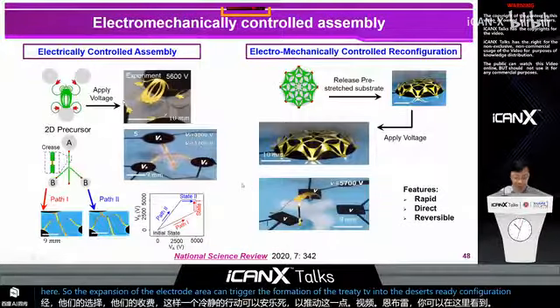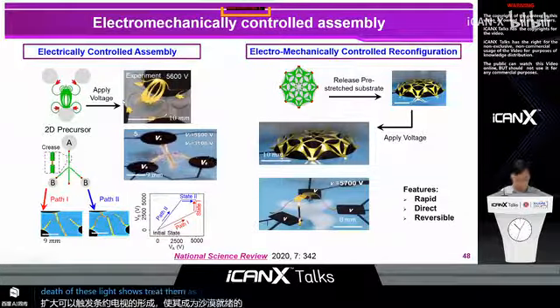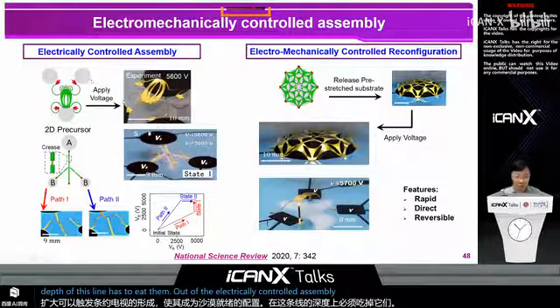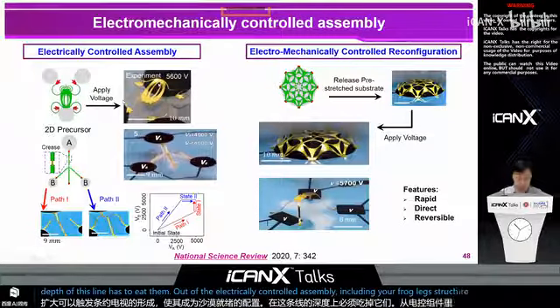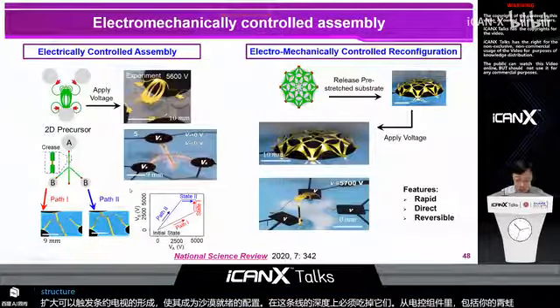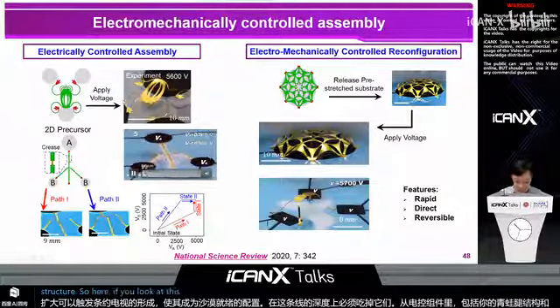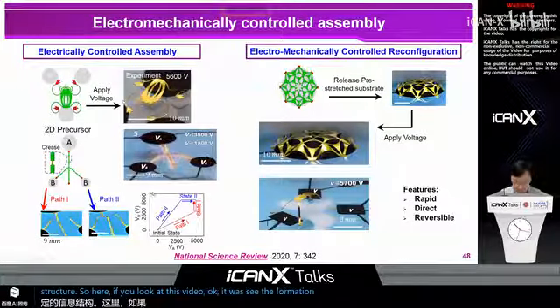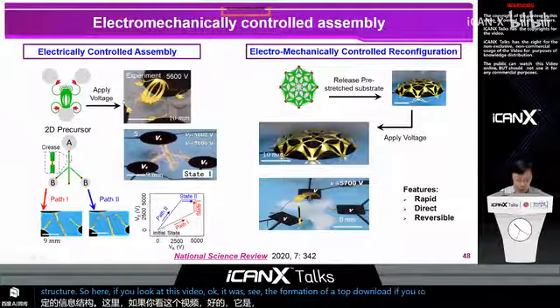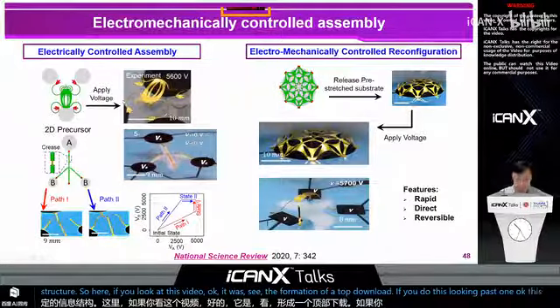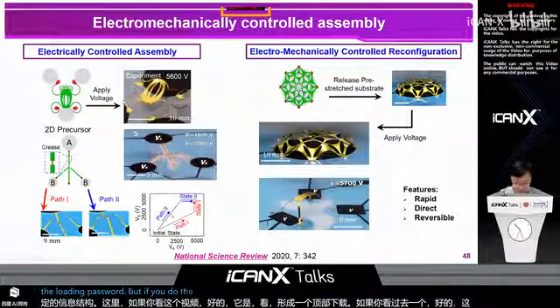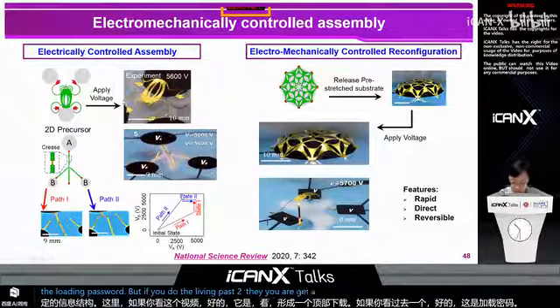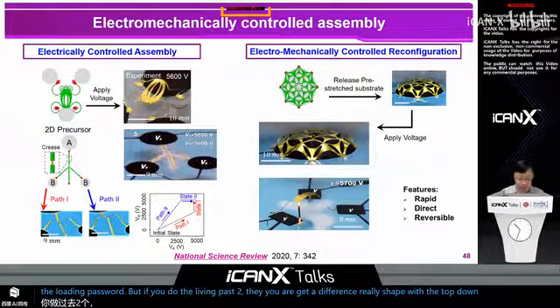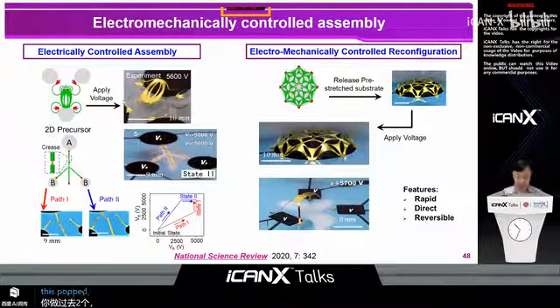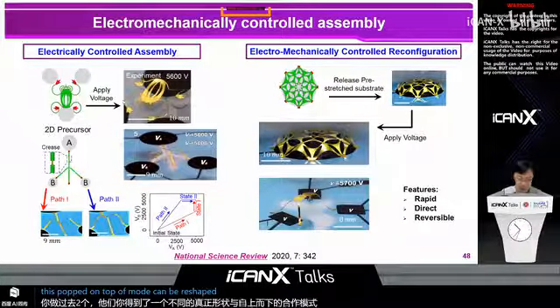On the left of this slide shows two examples of the electrically controlled assembly, including a frog-like structure and a bistable mesostructure. So here, if you look at this video, you will see the formation of a pop-down mode if you do this loading path 1. This is the loading path 1. But if you do the loading path 2, then you will get a different 3D shape with a pop-down, pop-up mode. And this pop-down and pop-up mode can be reshaped quickly between each other.